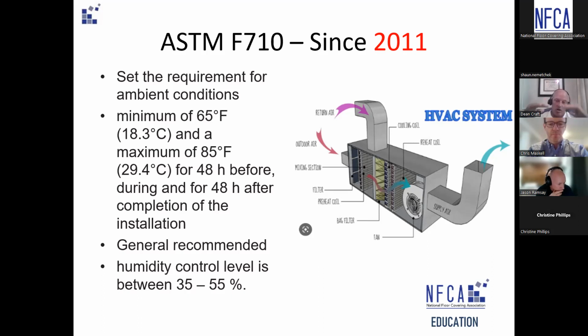The layer of the glue touching the concrete substrate surface just went to sleep. The top part tacks off, no transfer. You put your bond test down, 3 days later, you pull it up and it's a big wet spot. He goes, that's exactly what happened. I go, your slab's too cold. So it was, remember, this is 2011. And it wasn't until 2022 that the requirement to even evaluate the substrate surface temperature was added. And if you think about it, the substrate surface temperature is the really driving factor based on what the glue is going to be touching. So keep that in mind.